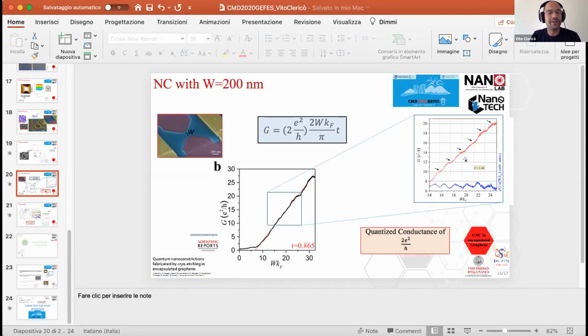I think it should be with the quality, but it's also with improving more the edge definition. Yeah, exactly. I think it's possible to improve. I think the bigger limitation now is the EBL. In the EBL process I use, for example, PMMA, but if I use a higher resolution resist, probably it's possible to improve more the edge definition of the constriction. Because I think that the quality of the graphene is quite high. Yeah, that's what you showed from before making the constriction, I guess. Maybe it's suspended graphene, but yeah.